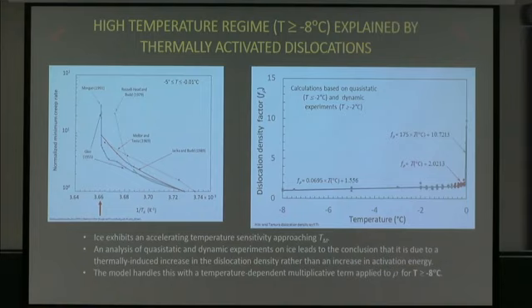But that was '71, and they pointed out that up to about -8 from lower temperatures, ice seems to have a constant activation energy. It starts to get higher, apparent activation energy. It gets higher, more sensitive to temperature, the creep rate does, with proximity to the melting point. So I normalized a bunch of results here. There's actually this blue line, an awful lot of results at very small temperature intervals, right up to -0.01 C, these Morgan results. You see, okay, this for your rate process people will recognize this, but typically the log of a rate versus 1 over T, the slope of that is your activation energy. So when you see things bending upwards, there's an apparent increase in activation energy.